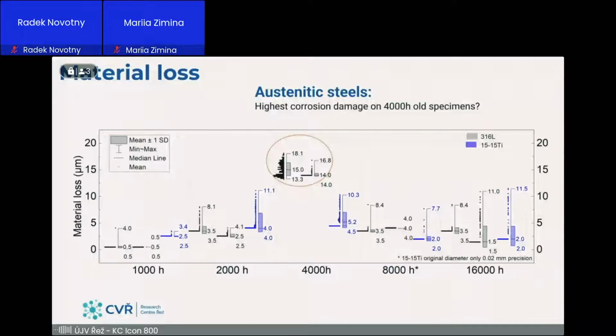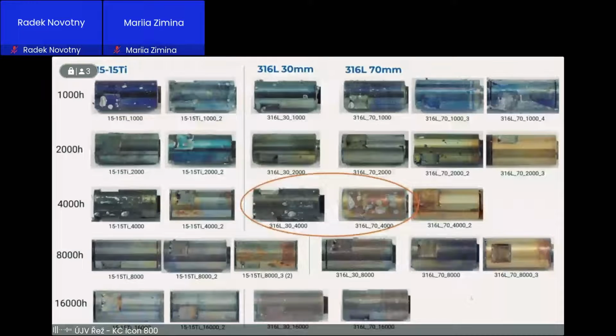Back to the austenitic steel that is more interesting. Why we have this highest corrosion rate of the 4,000 hour specimens was quite a mystery. We're talking about those two specimens. You can see that at the initial short exposure, all austenitic steels have a very thin oxide, it's blue, and then became thicker. And this black color indicates there is a formation of outer oxide similar to the ferritic martensitic steel. And we have the same oxidation rate, and this particular specimen looks intact.